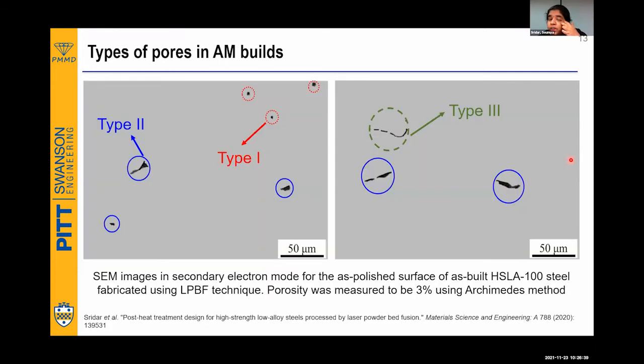So these are some of the types of pores which are found in one of our AM builds, I would say. So you see that the type 1 pores here are more or less typically spherical. The type 2 pores here, no wonder they are dangerous, as you could see, they are pretty sharp, and they are surely going to act as stress raisers. You can see this one, and so on. And type 3, you can clearly see a melt pool will be generally a cup-shaped melt pool like this. And you see that clearly there is a lack of fusion happening here, which is a type 3 pore, which, as I mentioned, is the reason why it is called low circularity, unlike the type 1, which is more or less circular.